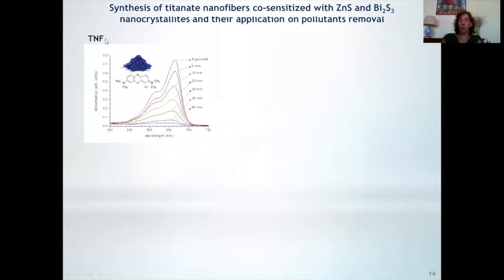And we decide to use this material for removal of a dye, in this case, methylene blue. If we look at the degradation of this product using titanate nanofibers, we have our solution, we have some absorption, and then we turn on the lamp, and we start to see that the degradation of the dye is happening here, and after more or less 1 hour, we have no signal of the dye.